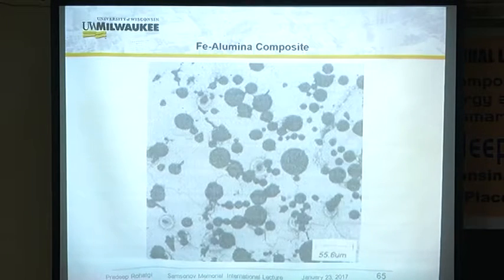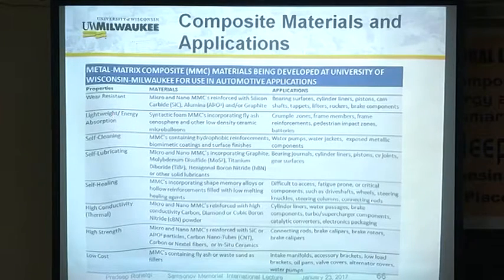This is the compressor that I had shown you earlier. People from iron and steel came. They said, hey, can you help me make iron and steel lighter? So this is spherical alumina particles in the matrix of ductile iron. And they allow you to make ductile iron stiffer and lighter. So there is opportunity in the area of iron also. This is from a paper we wrote in Advanced Materials and Processes, that you can produce wear-resistant, lightweight, self-cleaning, self-lubricating, self-healing, high thermal conductivity, high strength, and low-cost materials by metal matrix composites. And they can be used for cylinder liners, pistons, camshafts, lifters, rocker, brake components, water pumps, water jackets, bearings, journals, and so on, connecting rods. So this number of automotive parts can be made by these materials that can be produced in very, very simple foundries.